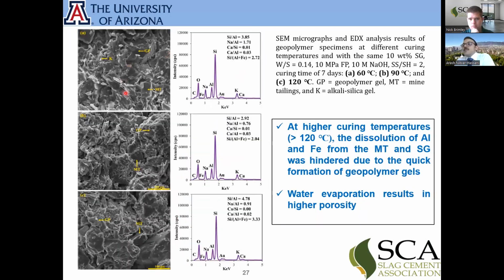And you see here in the graphs, by increasing the temperature from 60 to 90, the sample is getting more compact, but as soon as we go higher, we see more voids in the samples. And an interesting thing here too: if we go with a 90 degrees curing temperature, we see that the Si/Al plus Fe ratio falls exactly in the middle of the range that we discussed, and it's providing better geopolymerization that is good for producing durable construction material.